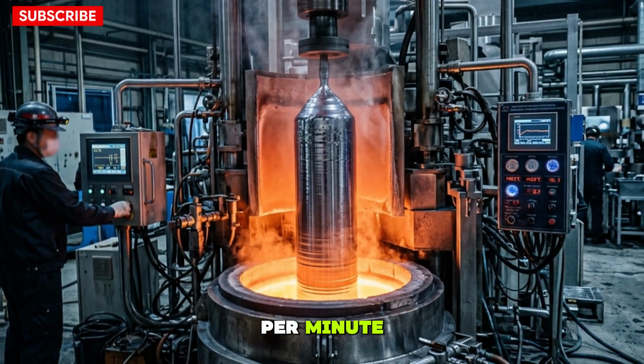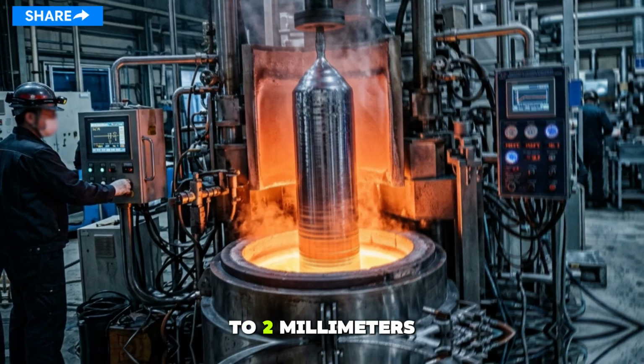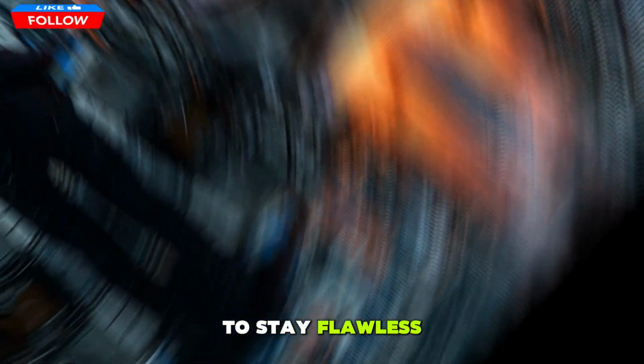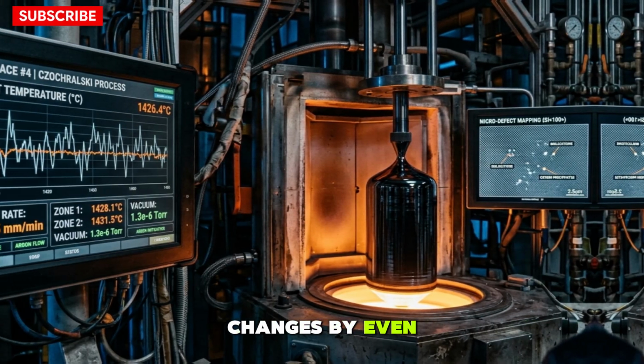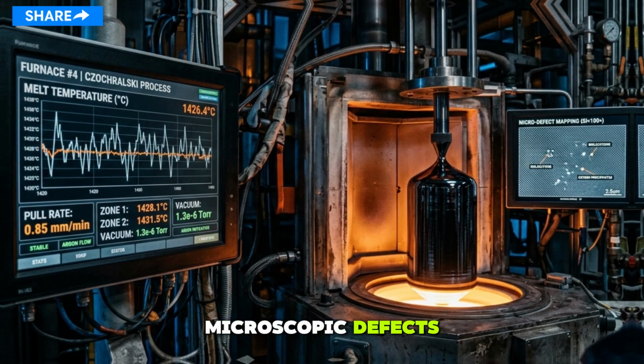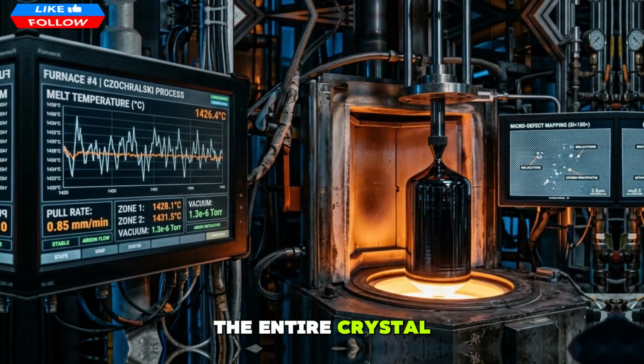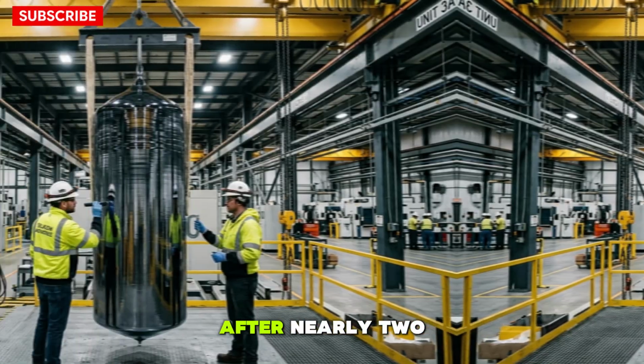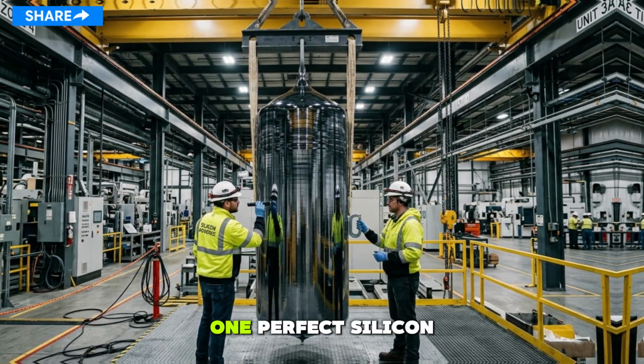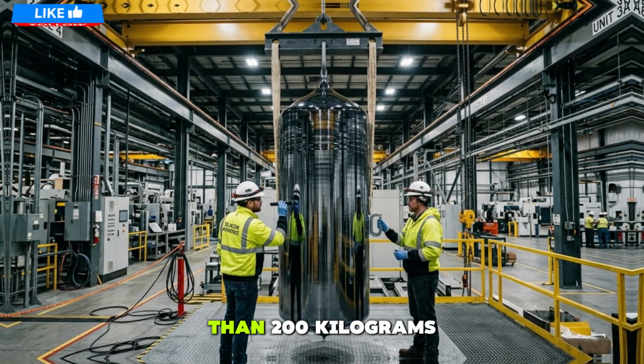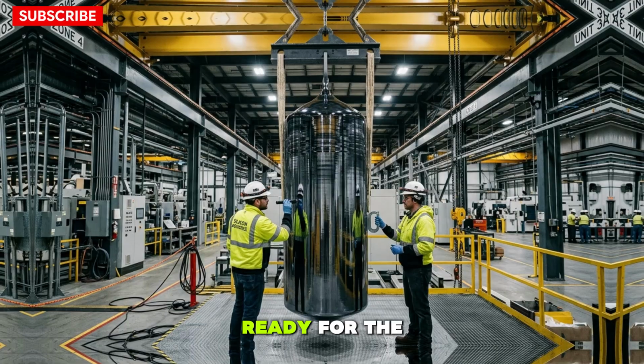The crystal rotates at roughly 5 to 20 revolutions per minute, rising just 1 to 2 millimeters each minute to stay flawless. If the temperature changes by even a few degrees, microscopic defects can spread through the entire crystal within minutes. After nearly 2 full days, one perfect silicon ingot can weigh more than 200 kilograms, ready for the next transformation.